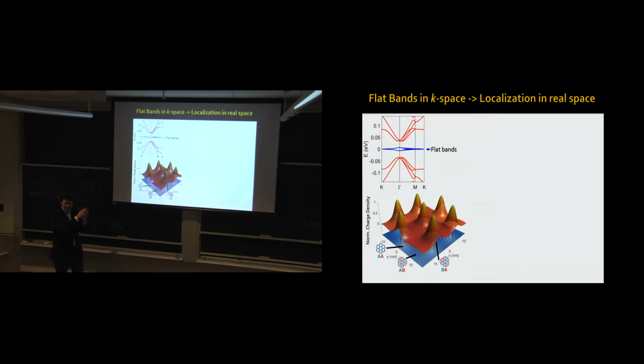Of course, in reality we have a small angle, so there's a shift towards a different stacking pattern, called AB stacking pattern. Only some atoms are on top of the other atoms - the B atoms are on top of the A atoms, but the others are not on top of each other. So these regions of high charge density are separated, tunnel coupled - the small tunnel coupling is what leads to the small dispersion - by regions of AB and BA stacking pattern.